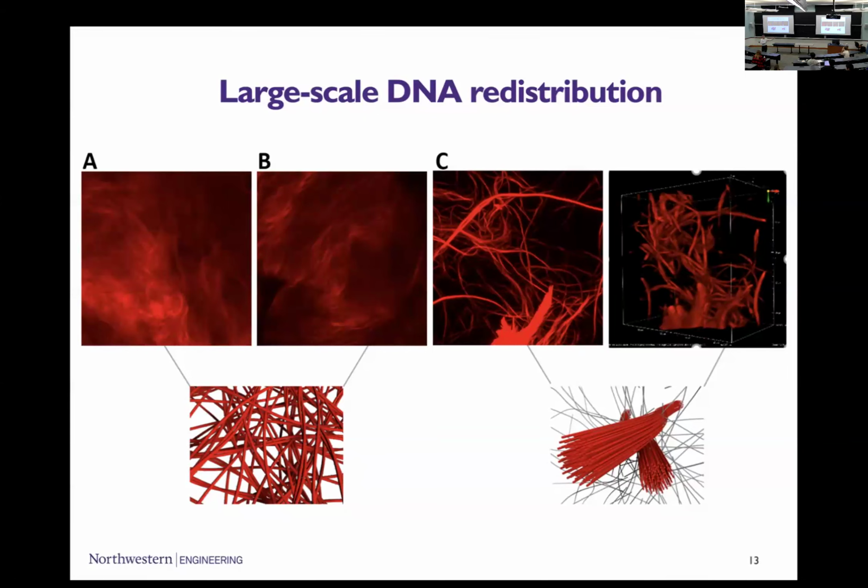So they don't see anything that is like supercoiling. They are not interested in it. So then I really have no reason to say, oh, could we do a simulation in which we see this? People have definitely done work like that in simple polyelectrolyte models. So let's say for DNA, where you take a semi-flexible charged chain, and you see if that forms a compact structure by, let's say, adding multivalent ions. Multivalent ions make polyelectrolytes aggregate. It is well known since a long time that if you add bivalent salt, the DNA precipitates out of solution. And if those chains are semi-flexible, you indeed get coils, at least. That's the very least that people have done.